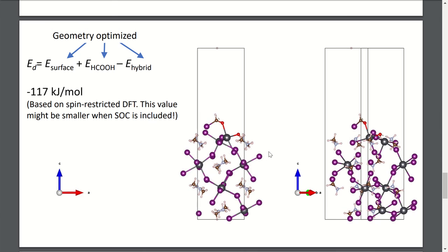There is a very big human influence in how you construct initial geometries. If you do something wrong, it probably will correct you, but not always. So what's the conclusion? We need to screen several initial guesses, several initial binding geometries, and select which of them are chemically more stable on one hand, and which of them give binding energies in reasonable agreement with experiment.